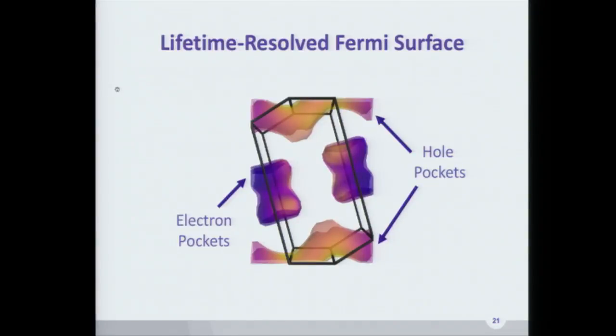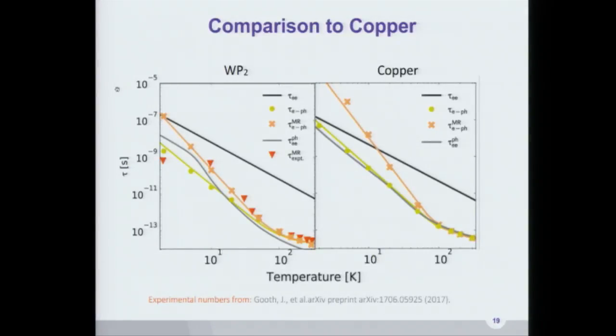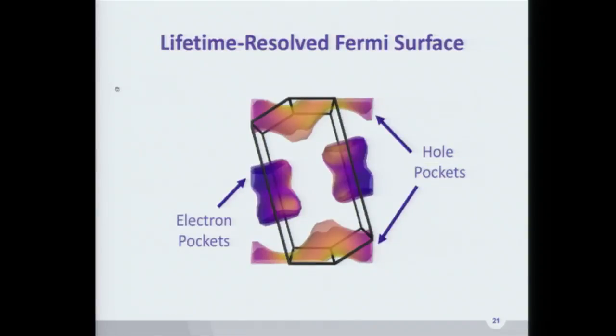Another thing that's really cool about this system is that the Fermi surfaces of these type 2 Weyl semimetals are pretty kooky. They have these electron and hole pockets. And we wanted to see if we superimpose the lifetimes that we had, because these plots here are only a subset of the data that we generate. We actually have the lifetimes generated across the entire Fermi surface, so we can superimpose them on the Fermi surface and see whether there are certain contributions from the hole pocket. By the way, this isn't just a projector thing. There is actually a layered nature to what happens in the Fermi surfaces of these materials. I was told not to call them nested because nested Fermi surfaces have a specific connotation, but the electron and the hole pockets actually have this kind of interlaced behavior.